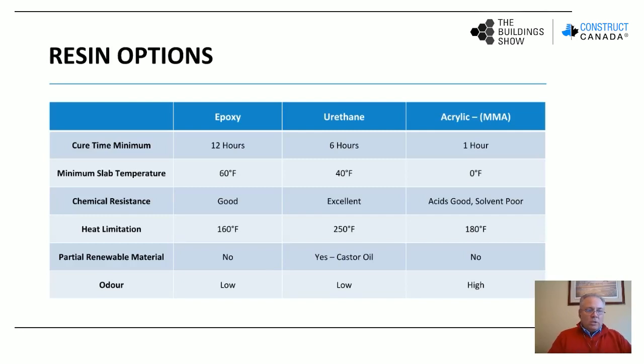If you'll notice, the epoxies, the heat limitation is about 160, and the heat limitation on a urethane is about 250. Well, it's not so much the ability to handle the high heat, it's more the ability to handle the change in heat. So epoxies generally don't react well to a huge spike in temperature, whereas the urethane can handle that very easily. So again, having a good partner to explain those differences is really critical when you're looking at different resin options and understanding the costs, the benefits, and the downsides of each one of these selections.